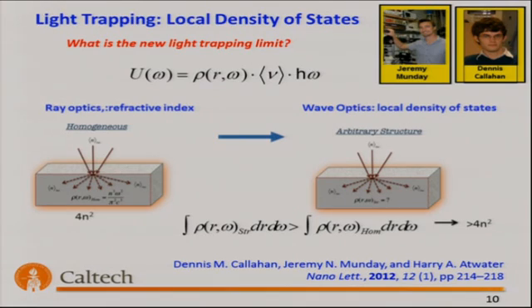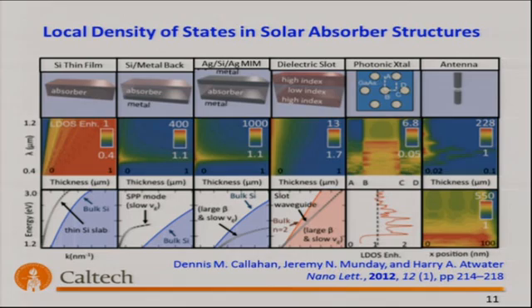But now when you get down to the wavelength scale, this local density of states becomes inhomogeneous, very inhomogeneous. And on the next slide, I've shown here the different structures for which the local density of states can be extremely inhomogeneous, such as a silicon thin film, and you can convince yourself that if you calculate the integrated local density of states in a silicon thin film, it's always less than the corresponding bulk silicon, which is a sensible result. I can't occupy as many modes in a thin film where I've constrained the number of modes as I could in the bulk.